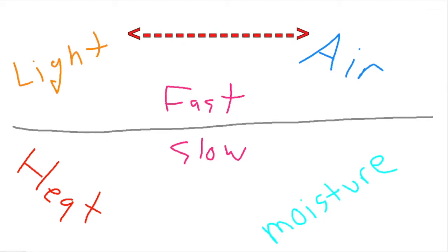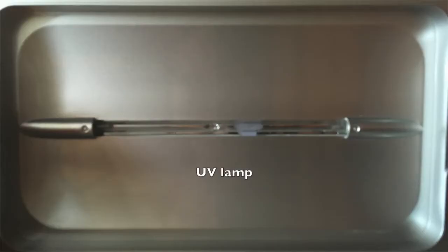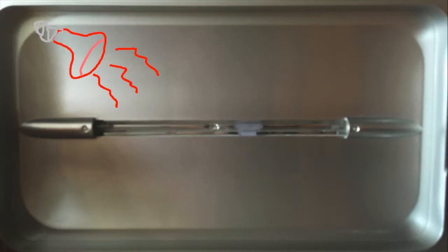So the double whammy for us seemed to be the one-two punch of light plus air, with light seeming to be the biggest offender, but greatly accelerated in the presence of oxygen, and then greatly accelerated again in the presence of oxygen and heat. Now, I'm kind of kicking myself on the heat thing because I didn't think of that ahead of time to run enough tests, so I only really have two or three data points. In hindsight, I also would have run an IR lamp along with the UV lamp experiments and then used definite, set time experiments and checked the brittleness along the way.